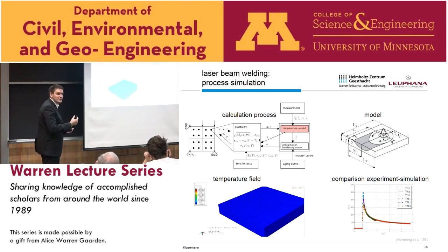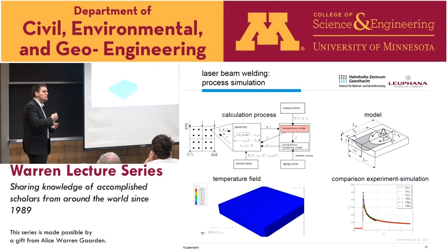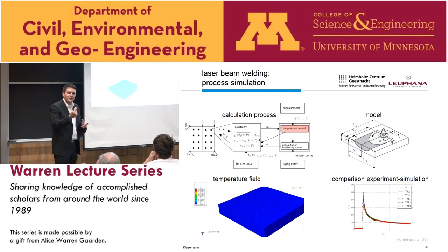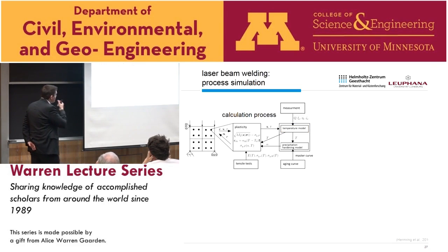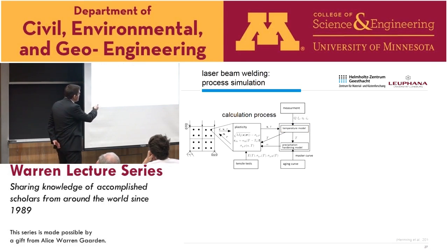This is the comparison between experiment and simulation, with respect to a thermocamera. We also had thermocouples, but we saw in the study that the thermocouples seem to be too slow. They're dynamically not accurate enough to capture these high gradients which we have inside of our structure. This is of course not in the keyhole, so it's not in the fusion zone, it's outside, otherwise it's hard to measure. In the keyhole you have probably a temperature around 2000 to 3000 Kelvin. Then we went to the mechanical part, of course.